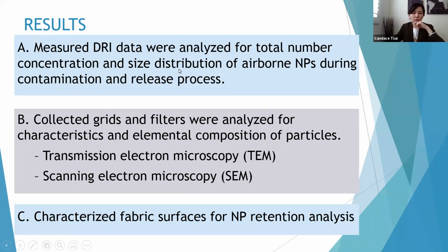The current data includes 3 different categories we have collected. The first category is regarding the actual exposure data from the mannequin's contaminated lab coat. We analyzed the real-time instrument data and came up with the concentration and size distribution to analyze the level of contamination and resuspension. The second category was characterization of the material we analyzed, such as the airborne particles collected on the filter or TEM grid, and also the fabric, which has been contaminated with nanoparticles.